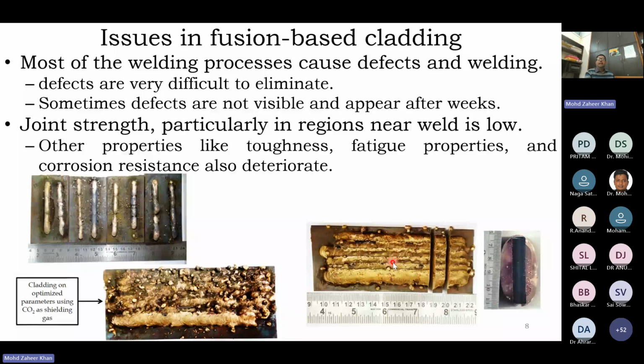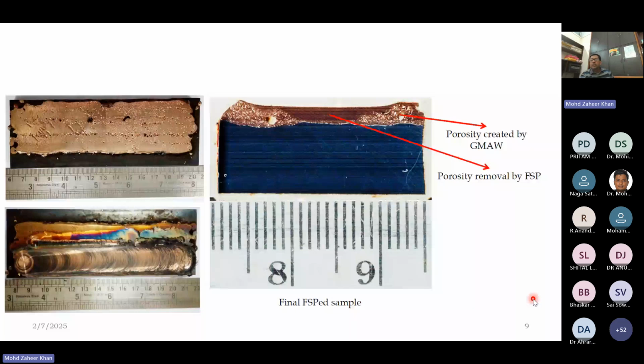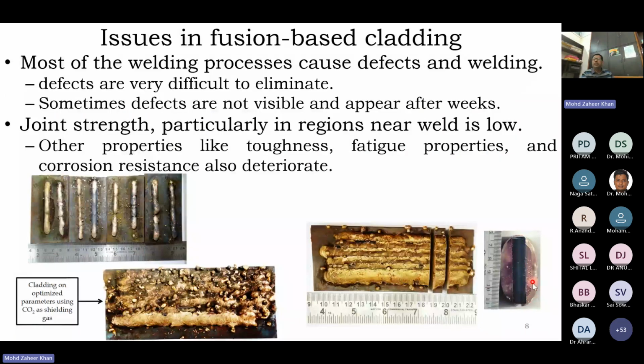This is the photograph of that, and the plates were cut to look at the inner cross section. As you can see over here, one complete layer of copper has formed on top of the mild steel substrate, but there are some problems that we are going to discuss. Although this is not very clear in these photographs, when we cut the specimen, mounted it and looked at the cross section, we found that although the copper on top seems to be nicely deposited, a lot of porosities were observed just below the surface of the cladded copper. These porosities will act as stress risers. Some of the porosities are open to the surface. The aesthetics of the material were also affected. So this porous layer of copper was not very desirable.